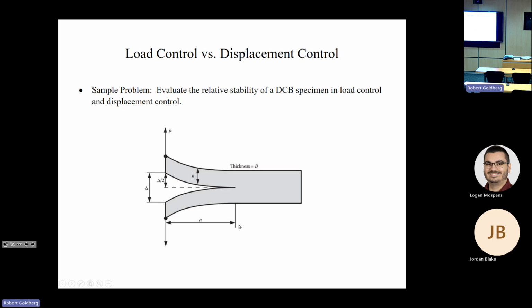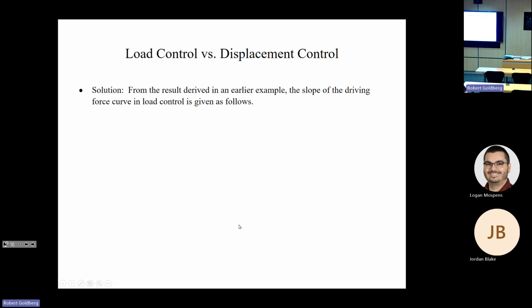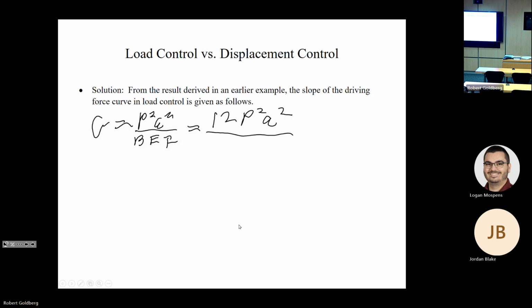So one more example problem. We're going to evaluate the relative stability of our DCB specimen in load control and displacement control. From the result derived earlier, we found that our strain energy release rate is equal to P squared times a squared over B times E times I. And when we substituted in the definition of the moment of inertia, we got 12 times P squared times a squared divided by B squared h cubed times E.